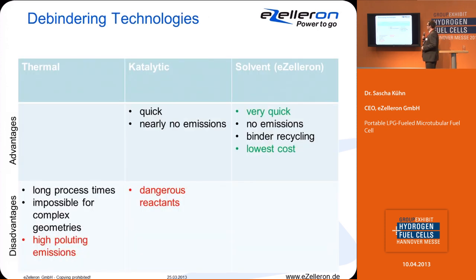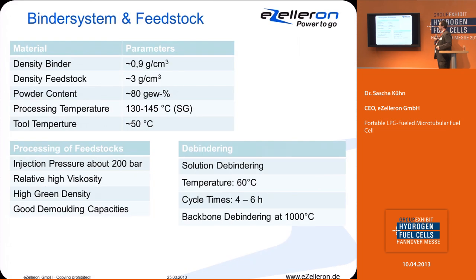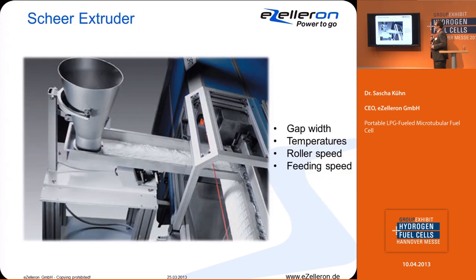And with our binder and debinding technology, we developed a totally new system for powder injection molding, which has a lot of advantages compared to standard debinding technologies like thermal or catalytic binder systems. In our case, we use solvent debinding, which is very quick and very low cost, and we don't have dangerous reactants or highly polluting emissions during the process. So it's a green process and also very cheap. This is about our binder system. If someone is interested, we can talk about it later.